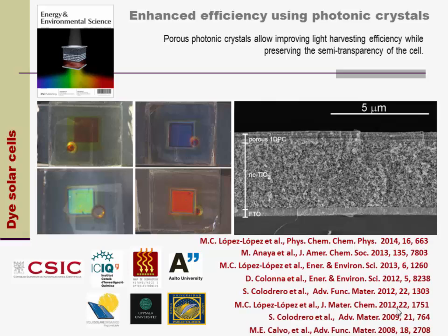Okay? Well, I'm going to make this story short because we spent a long time trying many different approaches, and we collaborated with different groups to optimize these. But finally, it was demonstrated that you can actually have this structure. What you're looking at here is again the cross-section of the device, but this part of the device now is a multilayer structure with nanoparticles. This is a Bragg mirror, a one-dimensional photonic crystal that is highly reflective.